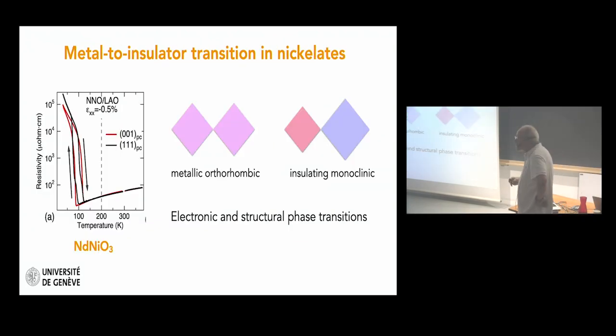The system I will discuss in great detail later is the metal-insulator transition in nickelates. So you see here one example, neodymium nickelate, resistivity versus temperature, metallic, transition to an insulating state. And also in this system, and you will see that it is very important, there is, along with the metal to insulator transition, a structural transition, and that was mentioned by Andrea yesterday. The material is metallic and orthorhombic at high temperature, but there is a structural phase transition, and the system develops a breathing mode and becomes insulating and monoclinic at low temperature.